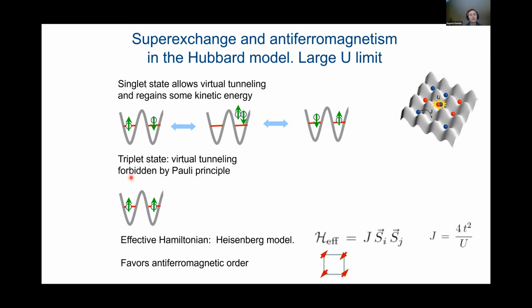Obviously, in this case, we prefer to have one fermion per site, but will the spins of these two fermions point the same way or in the opposite direction? You can immediately see that if spins are pointing the same way, then kinetic energy is fully suppressed because tunneling is not allowed by the Pauli principle. Whereas when spins are anti-parallel, the system can virtually go into a doubly occupied state and therefore lower kinetic energy somewhat. If one does this calculation, one finds indeed that this model can be written as a spin exchange Hamiltonian, where the super exchange J is given by the usual second order perturbation theory: the matrix element, which in this case is tunneling squared, divided by the energy denominator.